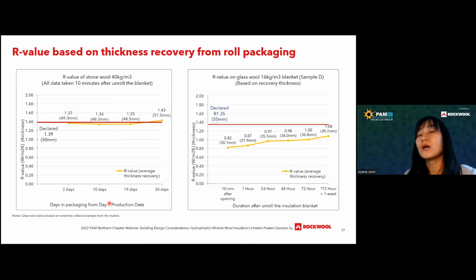So in this graph, we look into this performance. This is the comparison between 40 kg Stonewool and 16 kg Glasswool. Let's first look into the 40 kg Stonewool. What we did here is actually 4 different samples. Straight away from the manufacturing, we take the sample. After 2 days, we open it up and we measure the thickness.